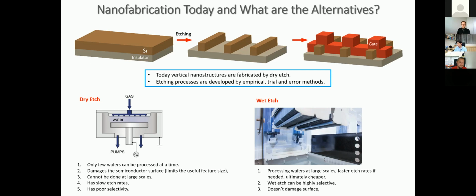So an alternative to it would be a wet etch, and wet etch is something that has been done for a long time conventionally, and you can process stacks and stacks of wafers in one go, and depending on your chemistry, it can be highly selective. And since it's a chemical reaction on the surface and not a bombardment, it actually does not damage the surface that much. So the wet etch has a clear advantage. So one of our mission questions was really to explore how wet etch works at the nanoscale.